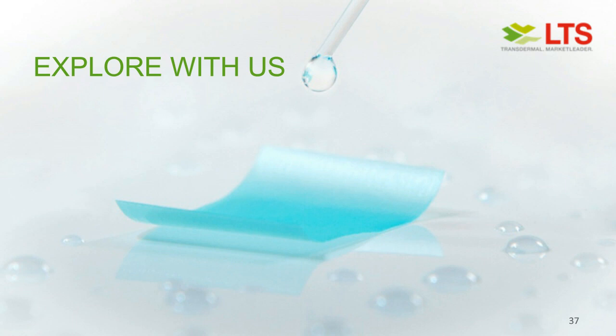Of course, there's a dose limitation. This comes along with the character of a thin film. Above a certain API content, it simply cannot be achieved because it would be a thick film, which would look like a flat tablet. So this is the limitation. But in general, if you're looking at a relatively fast PK profile within less than an hour or two, there are only a few limitations. If you're looking at constant drug delivery, like a controlled release tablet or very slow release over 24 hours, I think that's a different application and also a limit for an OTF, and maybe not the way we would look at it, because this is really a trans-oral mucosal uptake primarily and not through the GI tract.